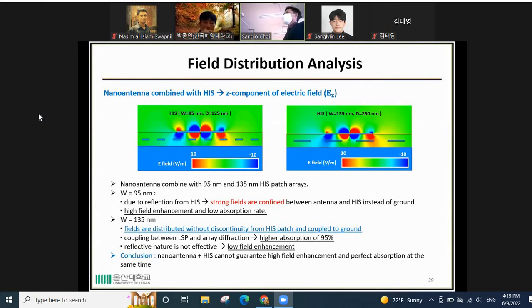From the 135 nanometer HIS, the field is distributed without discontinuity between HIS patches and also coupled to the ground line. This structure provides a higher absorption rate, 95%, because of the coupling between localized surface plasmon and array diffraction. In this structure, the reflective nature of the HIS is not effective, so it shows low field enhancement. Based on this observation, we conclude that nano antenna combined with HIS cannot guarantee high field enhancement and perfect absorption at the same time.